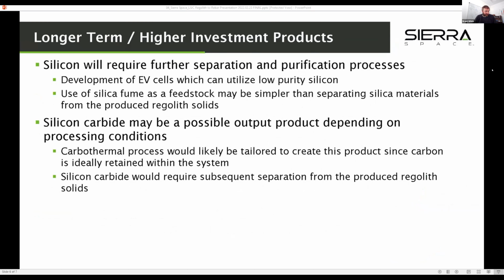So there's longer term things I think that would require more technology maturation. I know there are concepts out there for solar cells that can use a lower purity silicon. So our process could provide at least some feedstock for that. The silicon carbide is another potential product we can make. We would have to tailor our process conditions a little bit to make it. From our standpoint, we want to recycle that carbon and not lose it, but you would have to give some of that up in silicon carbide. So by bringing some replacement feedstock from Earth, you could make silicon carbide on the moon for the uses you need for it there.